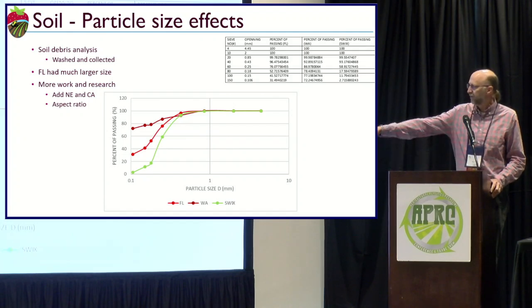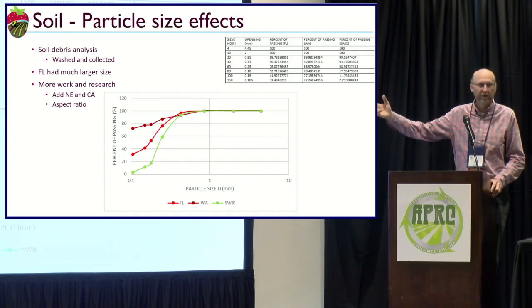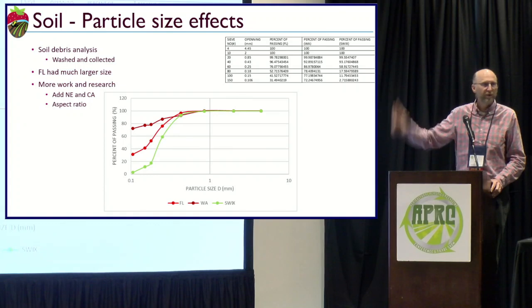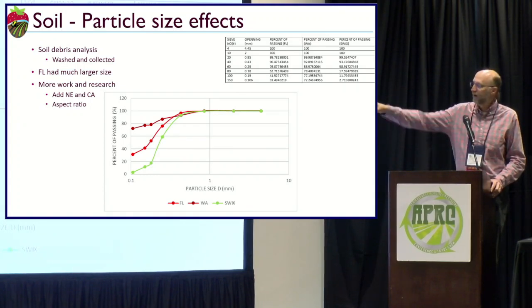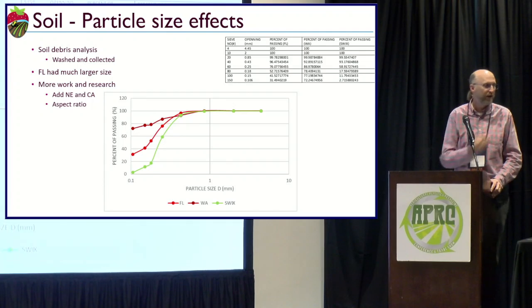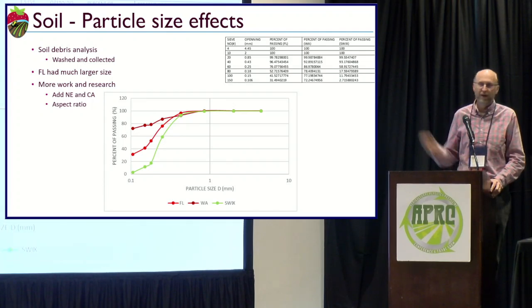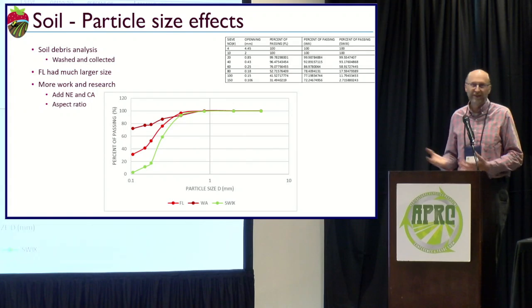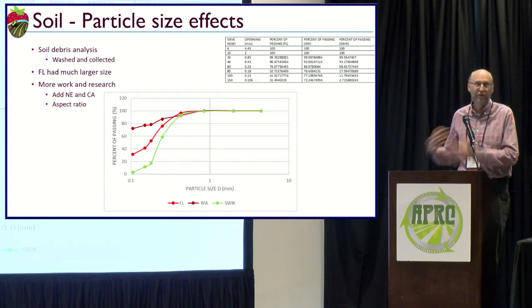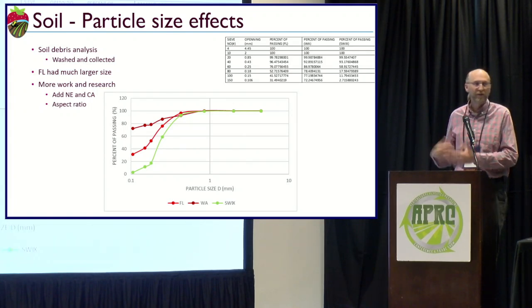You can see the Florida material and the SWK material are basically from the same area. They're huge particles. There's not a lot of small stuff in there, whereas the Washington is a lot finer material. It's probably going to stick to the plastic a little more. It may have a little bit more clay in it, so that clay is going to give that natural hydraulic cement kind of behavior.